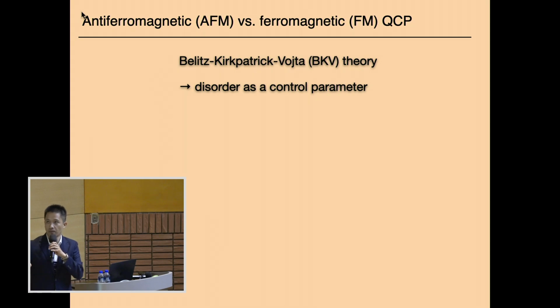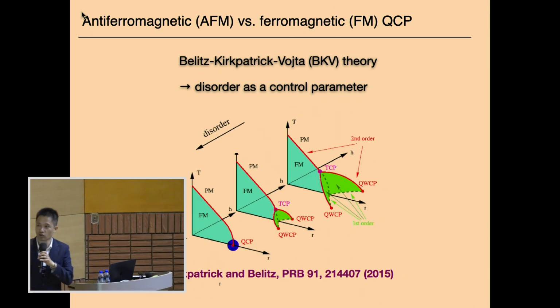Three physicists, Belitz, Kirkpatrick, and Vojta, BKV, proposed we could actually smartly take the disorder on purpose as a control parameter. And this is how the trick plays. For a clean ferromagnet, that's often the case: the second order phase transition, if you tune it, will end up at the tricritical point and continue by this fishtail, the first order transition. If we put in a little amount of disorder, the TCP temperature will be reduced. And also the area of this fishtail reduces. Finally, at a certain point, TCP will end up at T equals 0. And if you look at this phase diagram, this looks very similar to the generic phase diagram I've shown you a few slides before. So my work would be to test if this theoretical prediction works.